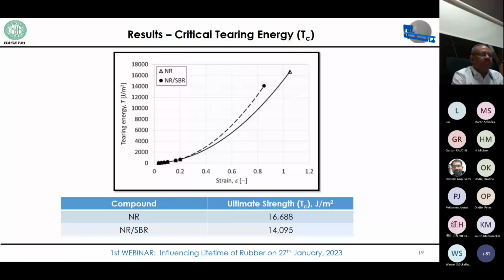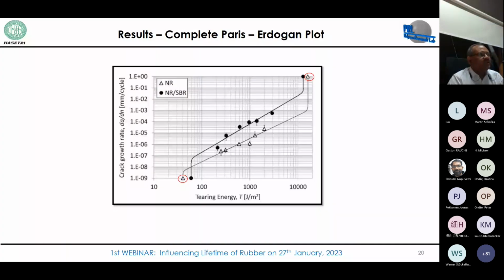So based on all this information, the complete graph was constructed, and you can see the red dots, that the threshold limit for NR compound is lower compared to the NR SBR compound. However, at the higher tearing energy zone, it is again showing the higher critical tearing energy. And of course, in the stable crack growth zone or steady state crack growth zone, NR compound is showing the higher value. So one should be very careful while interpreting this data and relating it with the practical application.